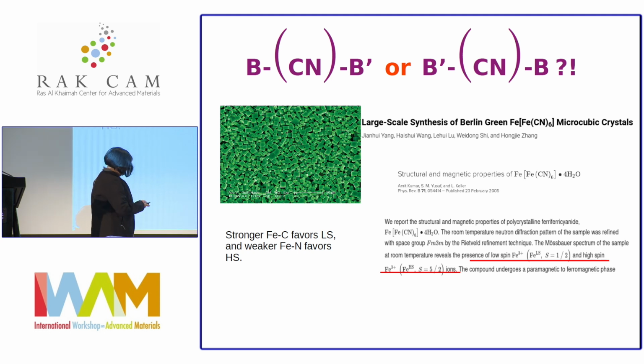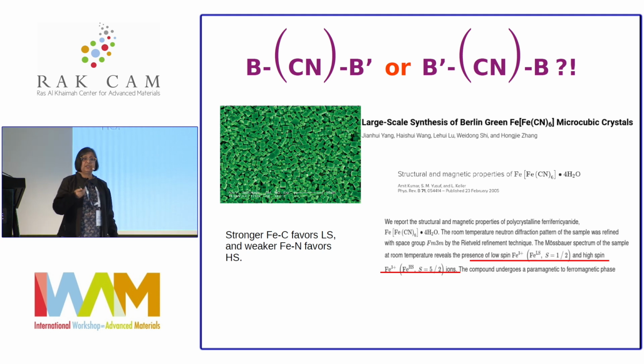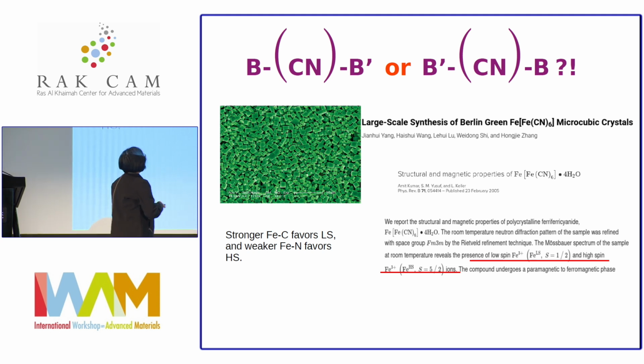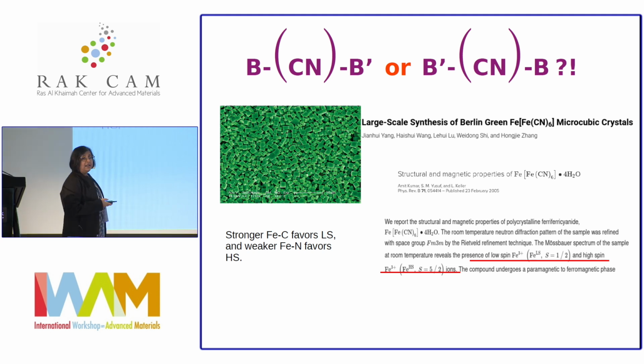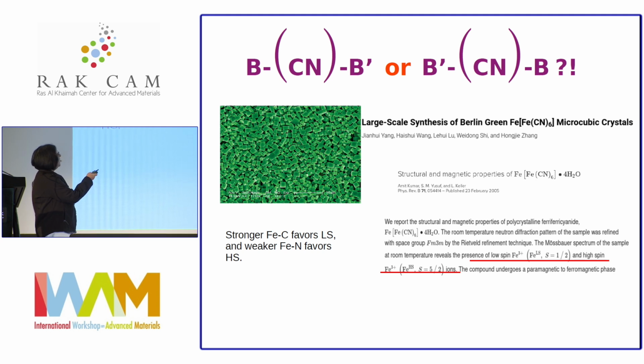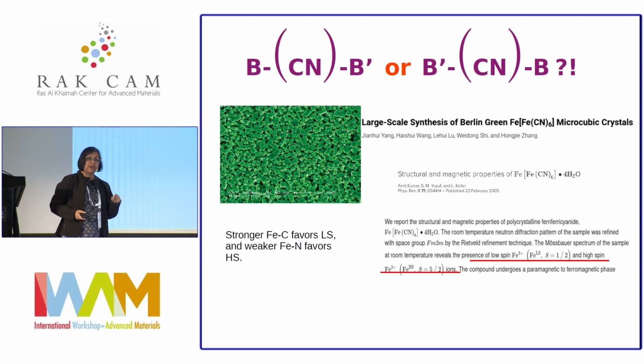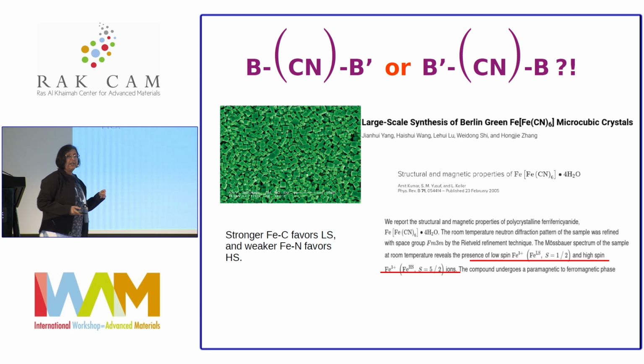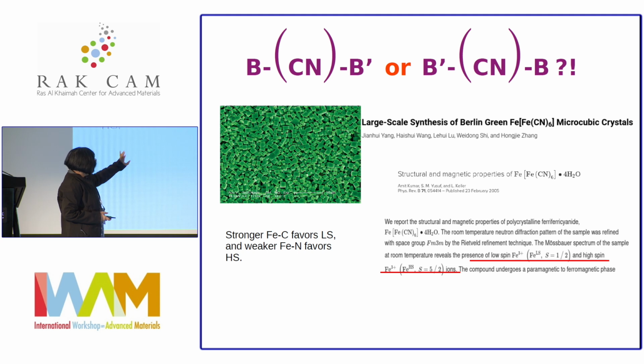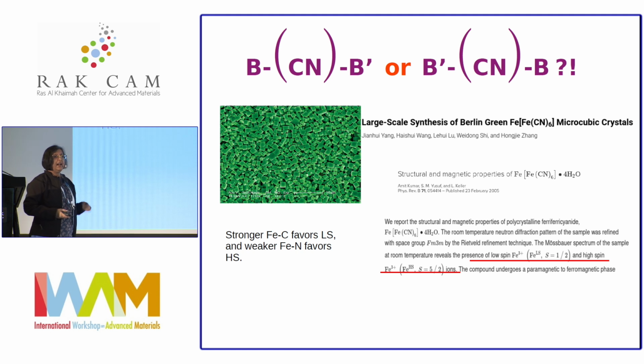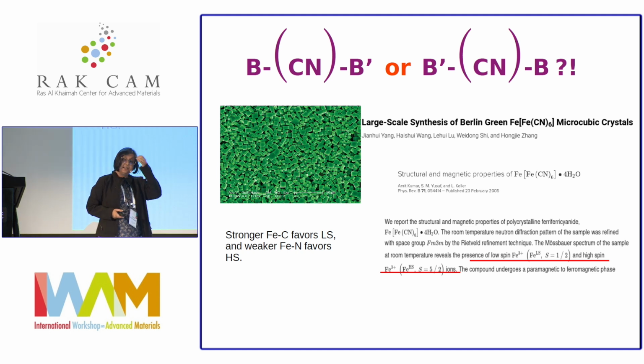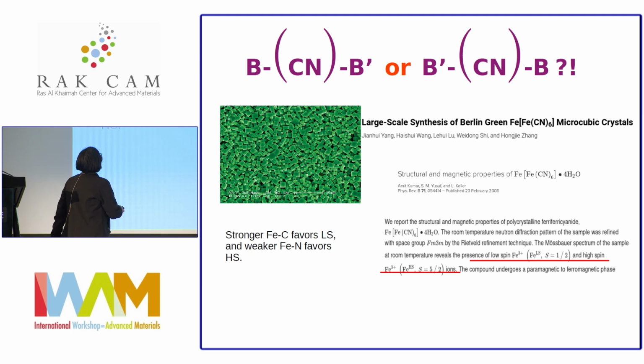And that's why it's very important to discuss with Tony, because he told me about this Berlin green, where it is also with CN, and iron is either in low spin or in high spin, and the iron connected to carbon is in low spin, while the iron connected to nitrogen is in the high spin state. So that tells me that the covalency has a role to play, at least. And other than covalency, what you can think of is the electronegativity. So that's all we did.